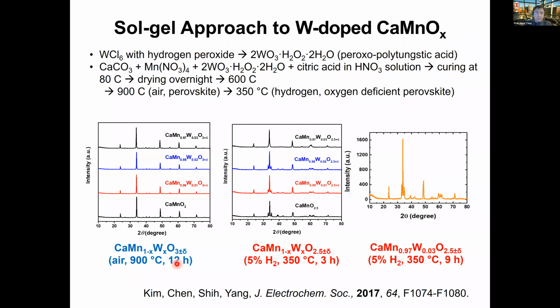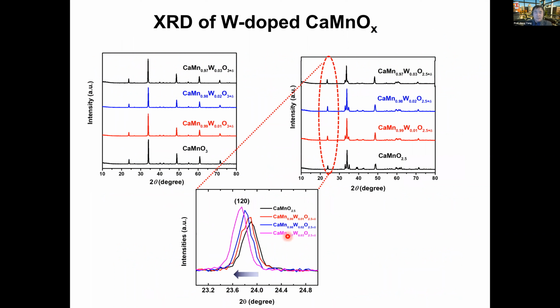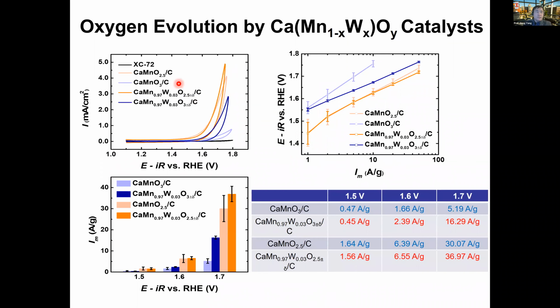For instance, if you look at this particular case for calcium, manganese, and tungsten, either the perovskite type or the defect type, the oxygen-deficient perovskite type, notice here the oxygen is 2.5 versus here the oxygen is 3. If you have tungsten put in, it can reach about 5% without seeing an additional peak in this particular case. If you look at the shifting from doping the tungsten, we see a slight shift, meaning that it is actually incorporated into the B sites. What we have observed is that the performance for the oxygen evolution reaction, in both the defect structure and the perovskite, gets slightly better, and one of them is much better than the other. So this is for the oxygen evolution reaction case.